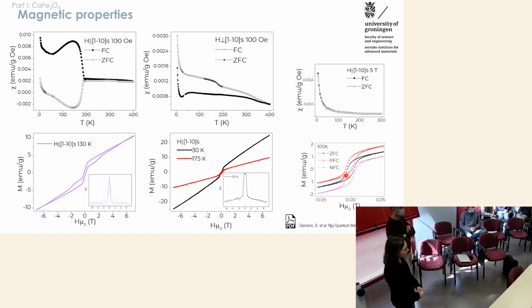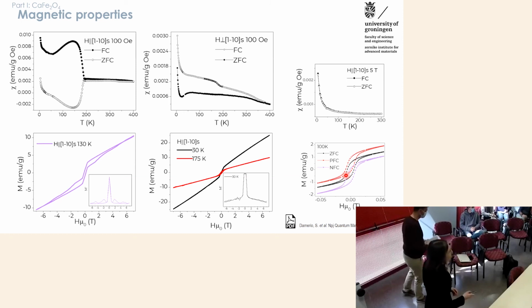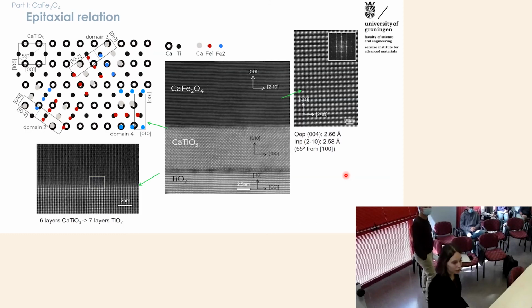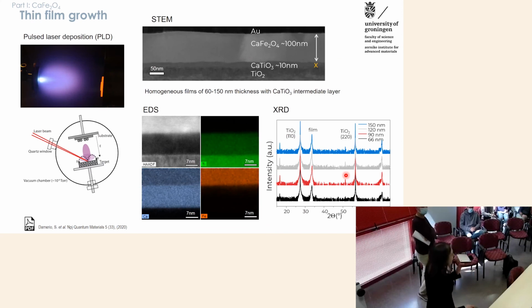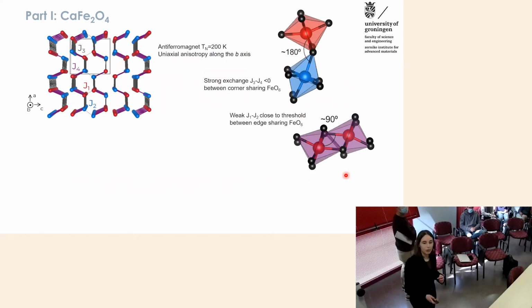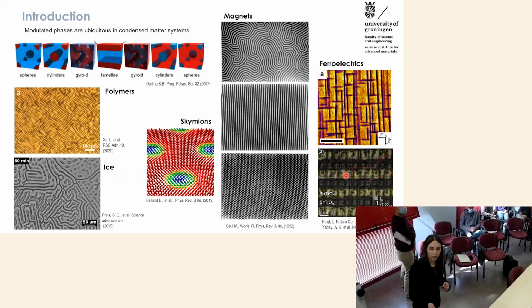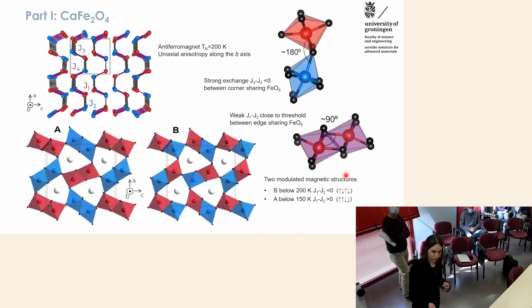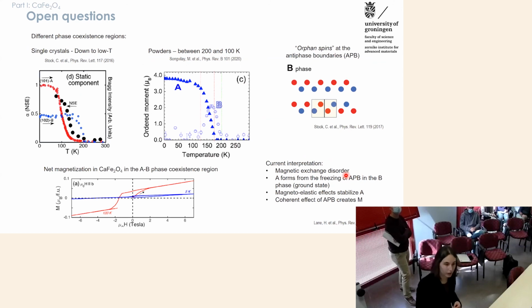These phases are incommensurate with the... No, in neutrons they give satellites or... That I know, they are commensurate, so they see very specific peaks belonging to one and the other because they don't have the same vector orientation. I'm not an expert on neutrons, but here they're plotting the intensity of the peak in the neutron experiment. So they can follow the 102 peak to follow the B phase and the 101 peak for the A phase. Yes, so it's good.